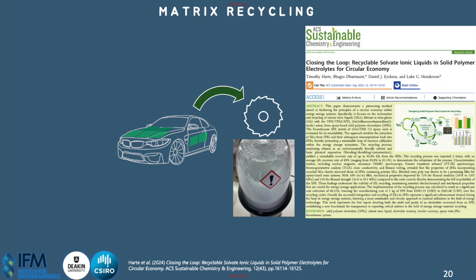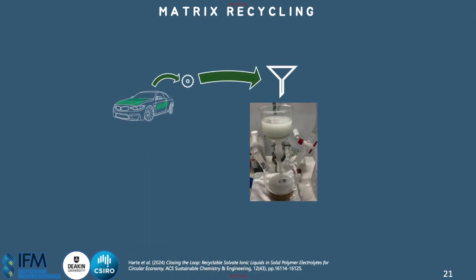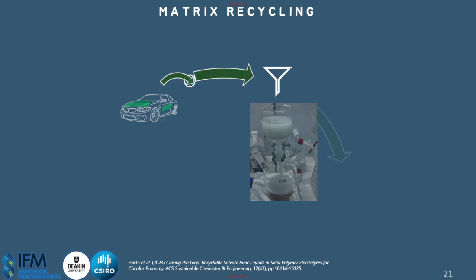And so we blended it with ethanol, which was chosen as a more environmental solvent, while having a high vapor pressure that allowed us to take it off under vacuum. And we initially vacuum filtered the blended filtrate and removed the filter cake from the liquid electrolyte, and we did multiple washes of this to improve efficiency over time.